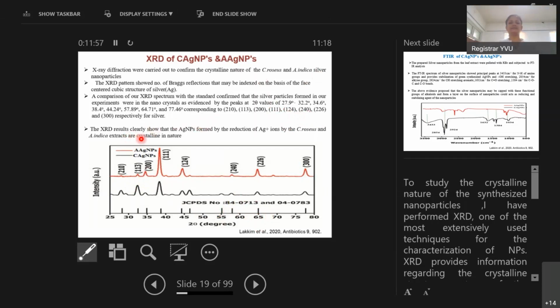The XRD results clearly show the AgNPs formed by the reduction of silver ions by the Catharanthus roseus and Azadirachta indica extracts are crystalline in nature. The black line represents the Catharanthus roseus silver nanoparticles and the red one represents the Azadirachta indica silver nanoparticles. These are in good agreement with the JCPDS numbers 84-0713 and 04-0783, which represent silver metal.